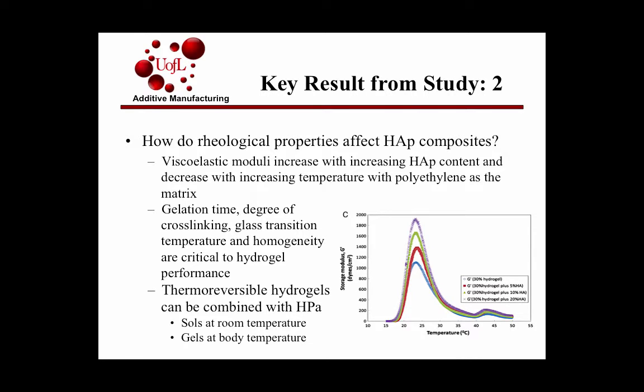For the HAP composites, the viscoelastic moduli increase with HAP content, and then they decrease with increasing temperature.